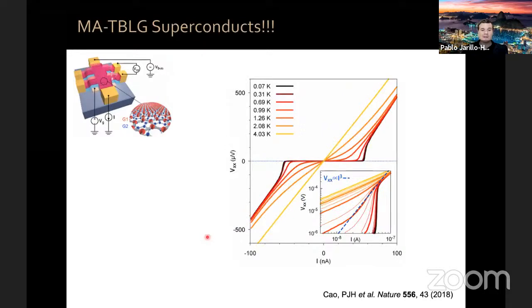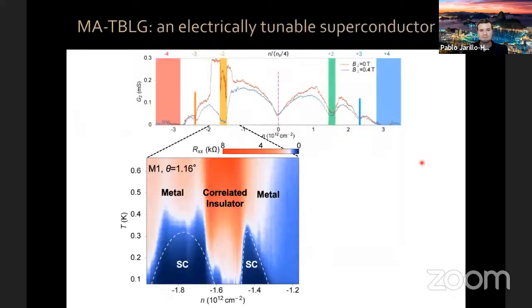Now, you can measure the VI curves. You can see here that we're running a finite current bias. There is zero voltage drop in our device. This is typical superconducting behavior until you reach the critical current at which it switches. You can do any test that you want to do of two-dimensional superconductivity. The system checks it. This is a two-dimensional superconductor.